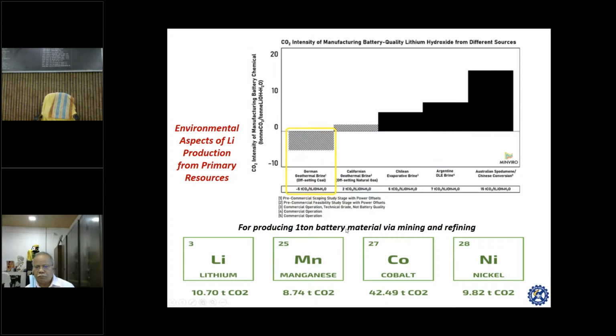So for producing 1 ton of battery material by mining, followed by concentration and refining, you actually make 10 tons of CO2 for lithium, 42 tons of CO2 for cobalt, and nearly 8 to 9 tons for manganese and nickel. This is what would definitely contribute to the GHGs. Of course, India will not be playing a role in this at this moment, but we might be definitely thinking about this, and these numbers of India might be changing the Paris Agreement.